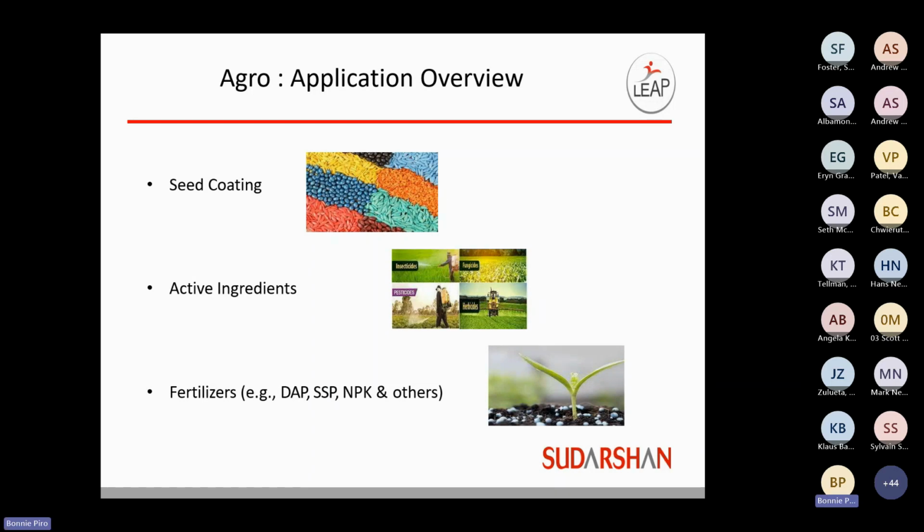There's also some more technical and performance aspect of it, especially when you include the mica effect pigments in there. The mica effect pigments add some additional slip when it comes to the seed application. The mica tends to remove the bridging effect that you might get in a hopper, so that the performance and productivity of the seed application is improved through that slippery surface.